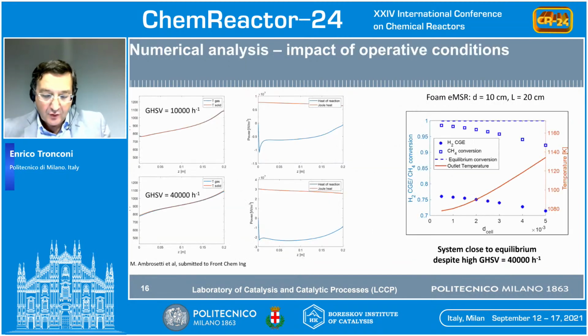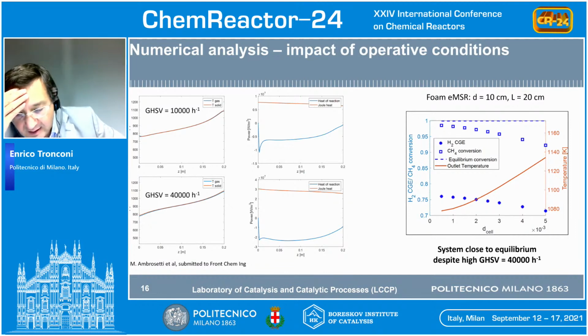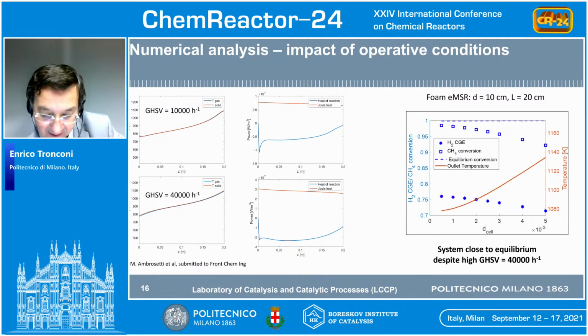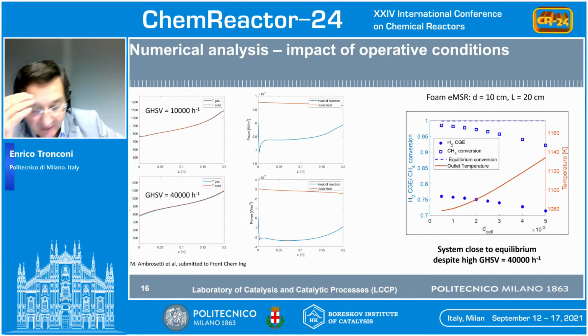Here we show some results of model simulations that we have run considering a hypothetical compact reformer for distributed hydrogen generation, a very small scale unit with a foam 10 centimeter in diameter and 20 centimeter in depth. Actually, the simulations show that this system can indeed be operated at very high space velocities, much higher than in the case of the industrial reformers, with very, very limited interface gradients.